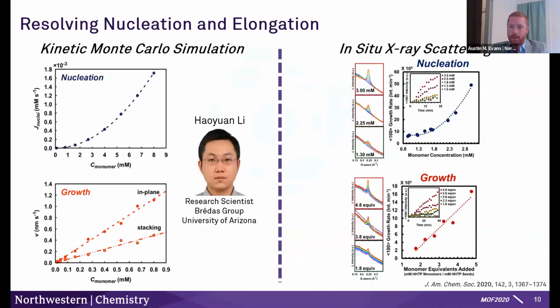So I want to go into just a little bit of the data on that. This all started with my colleague Haoyuan Li, who's a research scientist now at the University of Arizona, and he did kinetic Monte Carlo simulations to examine this growth and nucleation behavior. In the experiment, he puts a bunch of monomers in a box and parameterizes all of their different reactivities, whether that's bond breaking, bond forming, or interlayer stacking, which are things we can examine experimentally ex situ individually. Then you just let that simulation stochastically evolve. What he finds is that if he doubles the monomer concentration, the rate of nucleation more than doubles. It's a nonlinear process. That's in contrast to growth, where if you double the monomer concentration with a seed particle present, the growth is actually quite linear. It's a first order process.